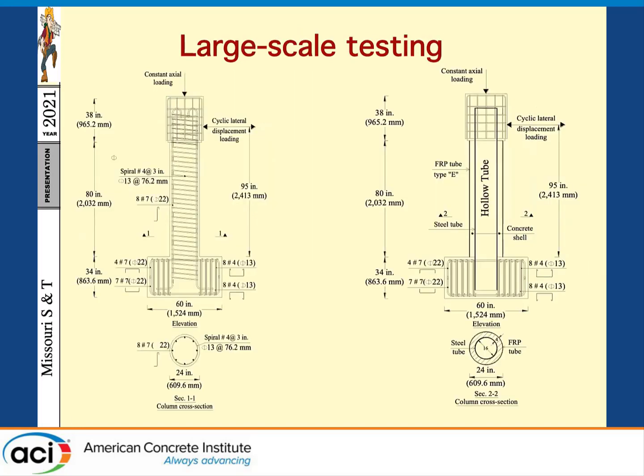So we took that idea to the lab, and we constructed our columns. The columns are almost half scale. The height of those columns is roughly 2.5 meters, and the diameter is 0.6 meter, with an aspect ratio of approximately 4. The one to the left over here is the reference column. It has a solid cross section and about 1.2% flexural reinforcement. That's 8 number 7 bars, and we also used a spiral. The spiral is number 4 at every 3 inches, going through the column.